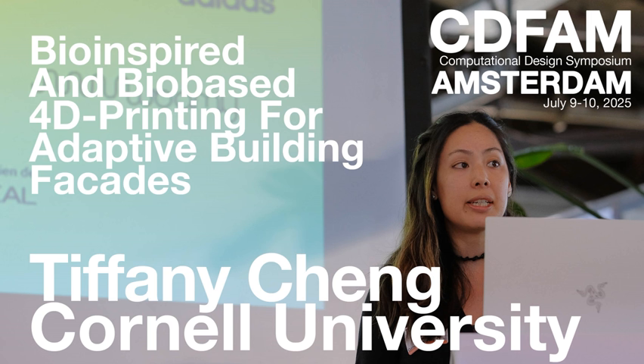And indeed, my partners from biology have found a 14 million year old fossilized cone that can still open and close. So this incredible robustness that we observe in nature often is due to the material structure. And you can see on the right here the cellulose microfibrils, which are arranged in these two directional layers. And this bilayer structure is what causes the pine cone to swell or shrink in response to moisture changes.